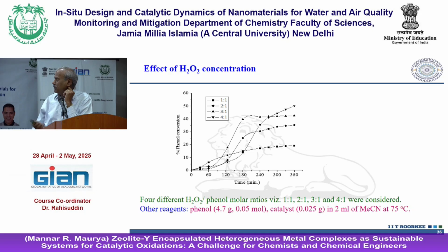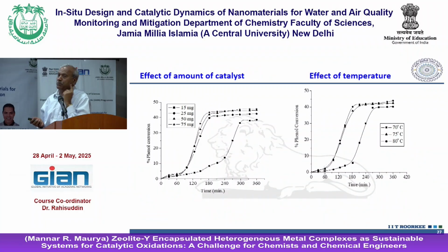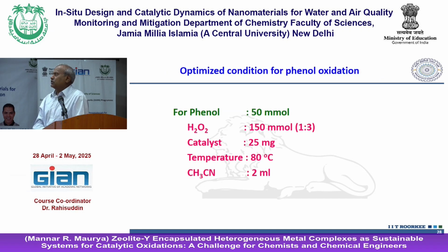This is related to H2O2 concentration. You will see that the best result comes at a certain condition. Then we have the amount of catalyst and the effect of temperature. When you look at all these things and combine them into the optimized reaction conditions, this is the one for phenol oxidation: 50 millimole of phenol. 50 millimole is too large an amount, but we started with that. And H2O2 you require almost 1:3 ratio, catalyst 25 milligram, temperature 80 degrees. Minimum solvent is required to do this reaction.